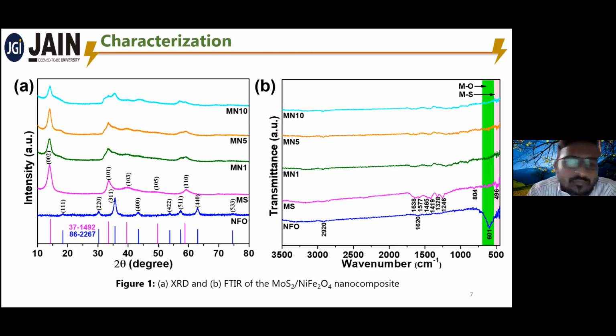In XRD, we can see that pure MoS2, represented as MS, and pure nickel ferrite, labeled as NFO, are well matching with the JCPDS files, and no other impurity peaks are observed, which clearly suggests that no impurities are generated in the materials. In the nanocomposite, we can see that the intensities of the peaks are slightly reduced. This may be due to a slightly amorphous nature and decreasing crystallinity. But the peaks of both MoS2 and NiFe2O4 are clearly present in all three hybrids, labeled MN1 for 1 mg, MN5 for 5 mg, and MN10 for 10 mg addition. XRD also evidences that the MoS2 is in the 2H phase while the NFO is formed